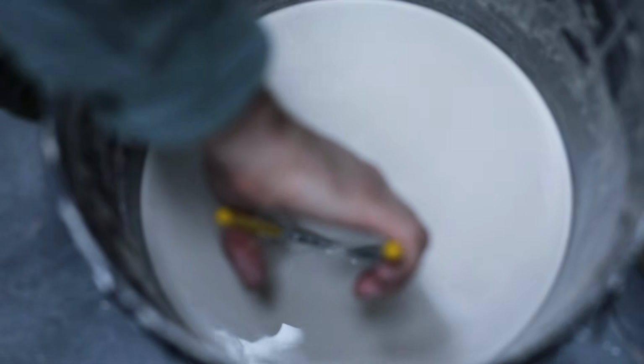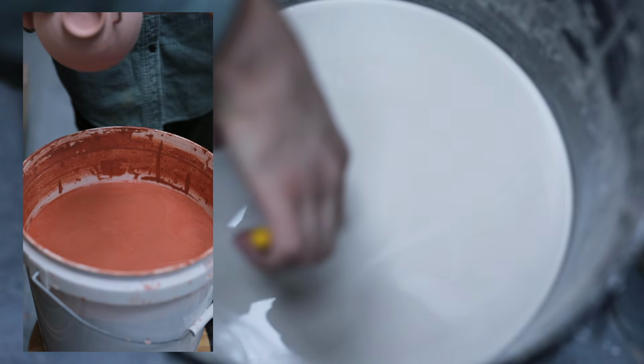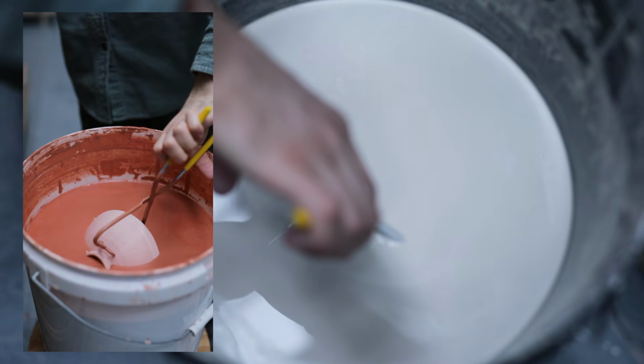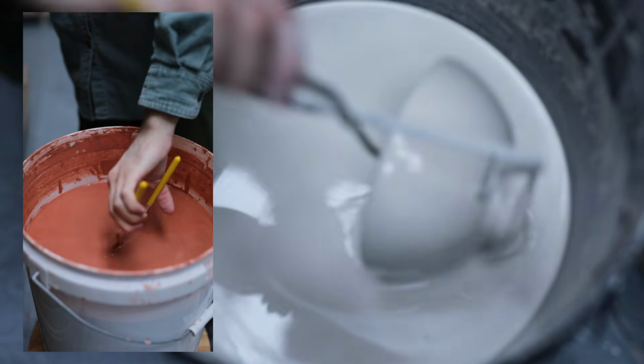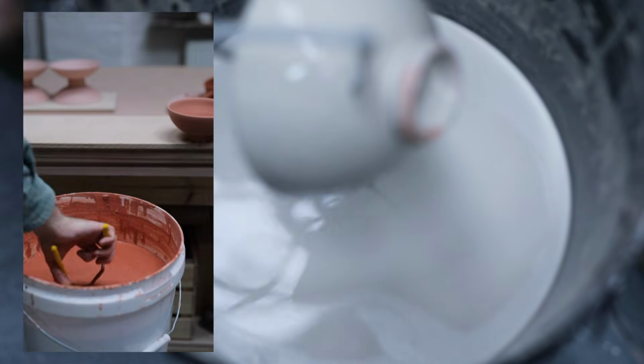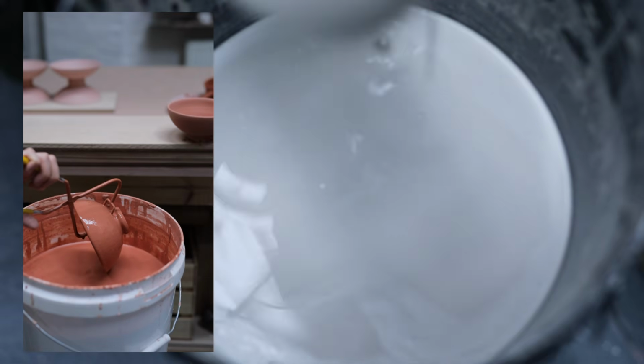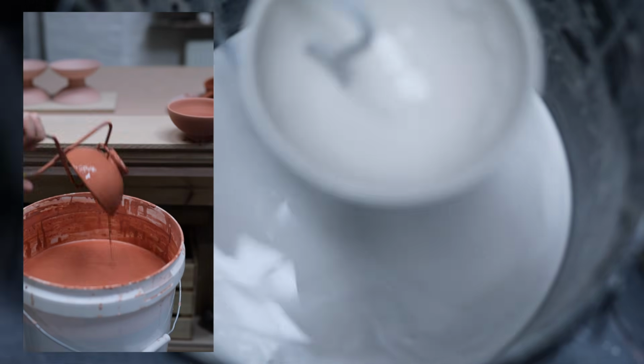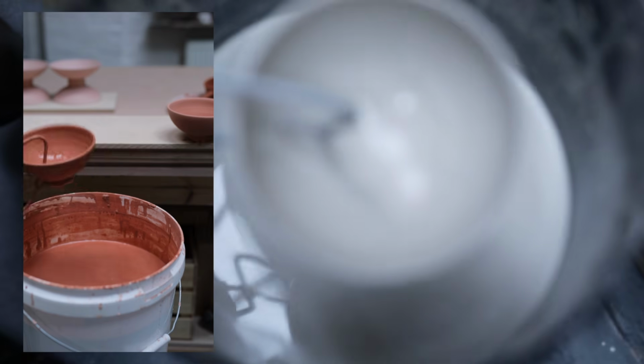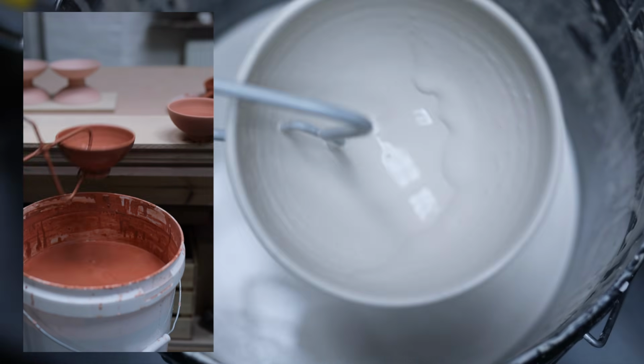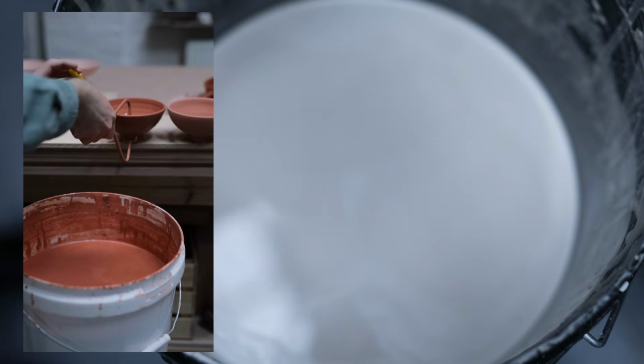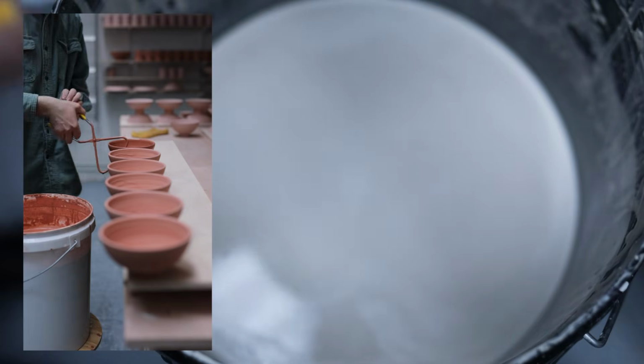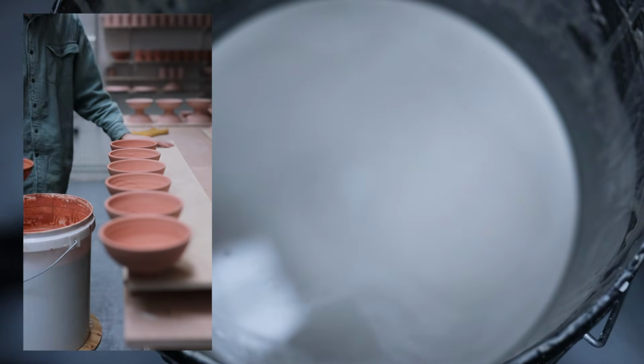This white will turn a greyish colour once fired, and then if I add 1% red iron oxide to this glaze, the end product, once reduction fired, will be a pale green tone. I have another glaze too that's 2% iron, and that will be an even deeper, darker green, and beyond that the greens begin to turn brown and then finally black as more red iron oxide is added to the original base glaze.